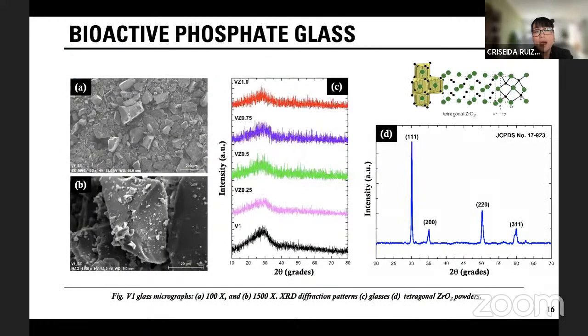This slide shows part of the article results, which illustrate the amorphousness of the glasses and the irregular morphology of the glass powders. These images were obtained by a scanning electron microscope. The last image shows the diffraction pattern with the tetragonal crystalline structure. The zirconia acts as a nucleating agent, helping the glass crystallization.